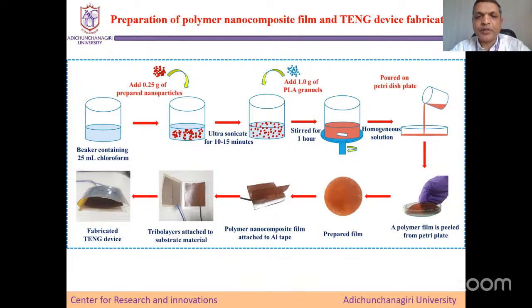Once the film is prepared, it is attached to aluminum tape so that it can capture the current. The tribo layer is attached to substrate materials, and this is the fabricated device. You can see there's a hole, and when we tap, you get different current.